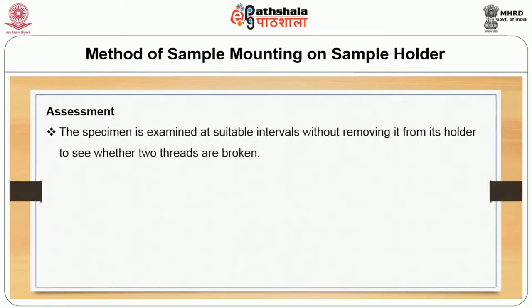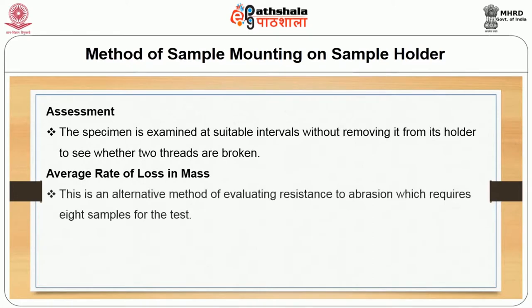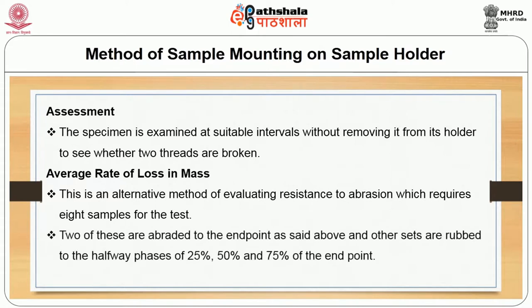Assessment: the specimen is examined at suitable intervals without removing it from its holder to see whether two threads on the woven fabric are broken. An alternate method to assess the abrasion capacity of the woven fabric is the average rate of loss in mass. It's an alternative method of evaluating the resistance to abrasion for woven fabrics, which requires 8 samples for the test. Two of these are abraded to the end point as said above, hole formation or change in weight.